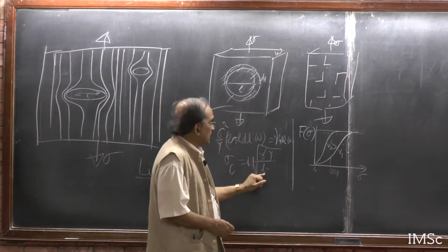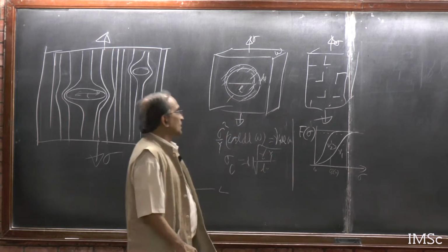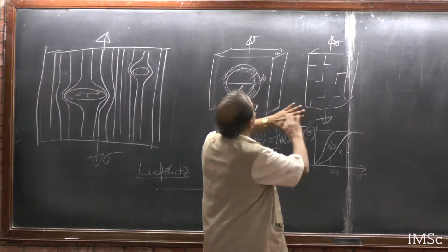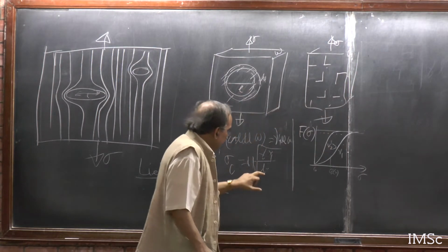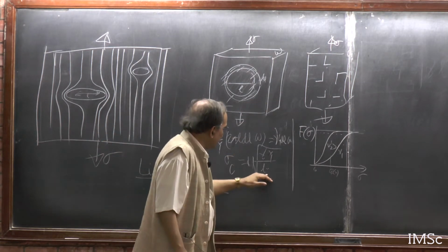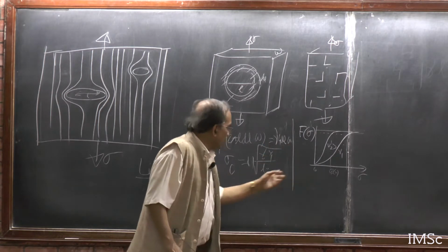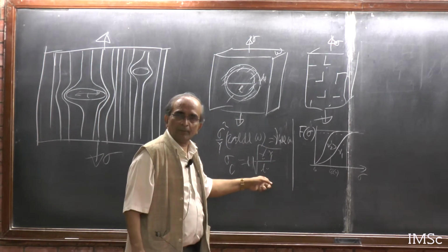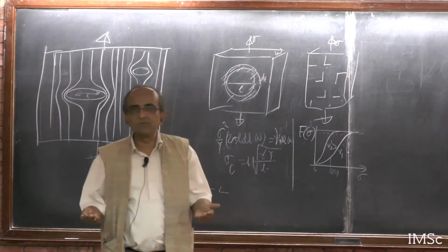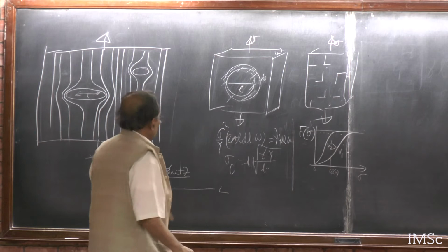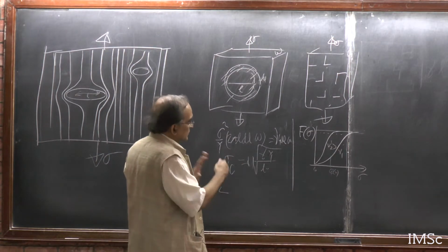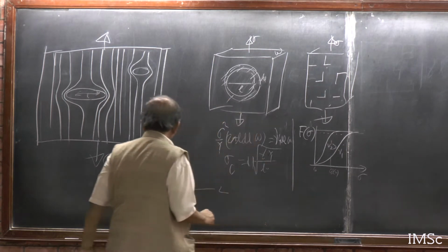But what we wanted to tell is that if you have a disordered system and there is no one dominant enough, then there is no clear L that has to be used. If you do the calculation properly, you will find that instead of L, some volume dependent term will come, a log volume. And so in the limit volume going to infinity, the system fails at any point. That means this is not a defined quantity, because it has a statistics which is not self-averaging, and that is what our intention was.